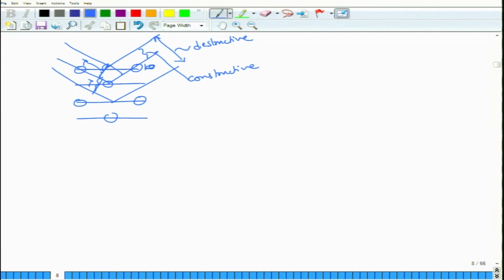Okay. So at smaller angle, the path difference is such that when you look at first order 1 0 0, the path difference is lambda by 2 and lambda by 2, they all cancel each other, nothing diffracts. When you go to higher angle, this path difference becomes lambda, and this also becomes lambda. So this is at lower angles when the path difference delta L is lambda by 2 between the successive planes.